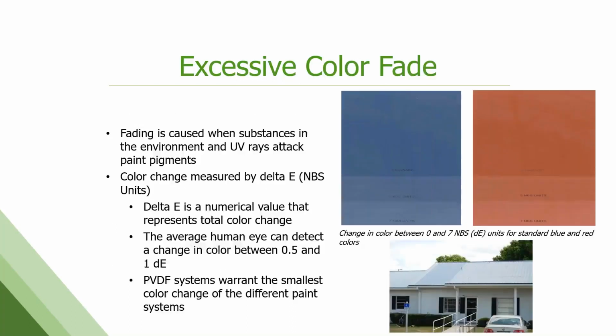Color fade is probably the biggest one and probably the most important one in the exterior building world, right? We don't want it to fade, or we don't want it to fade too much over time. So fading, of course, is when UV degrades the pigments itself. Color change is measured by a delta E value, a numerical value that we use an instrument to measure. The average human eye can start to pick up a color difference in the 0.5 to 1 delta E range. The Kynars, the PVDF, tend to have the least amount of fade and are warranted as such.